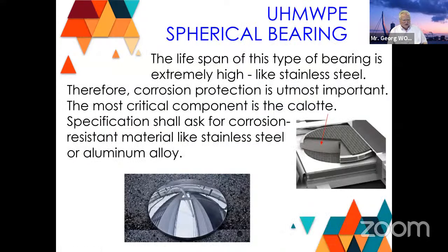And then there are some details which still needed improvement, because the basic steel parts have a corrosion protection, but for the calotte, it's very difficult. You cannot make a very thick paint under the material, and so in the first bearings it was a chromium plating, but that was not so good. We mean this bearing has the same lifespan as a structure, so it may be 100 years, and people had some doubts about the corrosion, and so today it's state of the art to produce this part, the calotte, from a corrosion-resistant material like stainless steel or aluminum alloy.